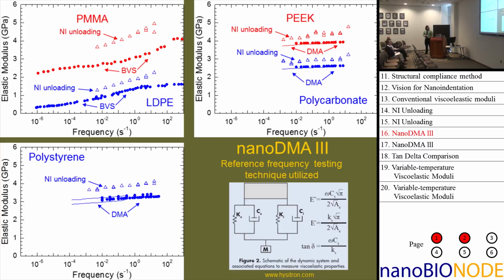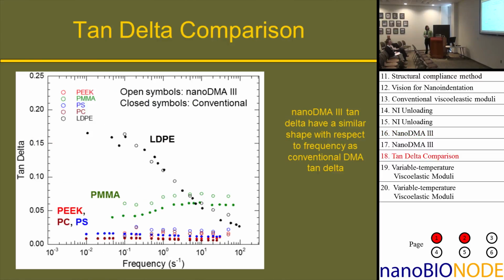So there's, of course, another way to try to measure the viscoelastic moduli, and that's to do these dynamic tests, where basically you load up the indenter and then apply a sinusoidal load to it and measure the load and displacement, and you can calculate a storage modulus that way as well. And we do that on these exact same experiments. Again, we see that it's always systematically higher, but we continue to capture the shapes of these curves. So another thing with the dynamic indentation is that you can also easily calculate a tan delta. And the tan delta is related to the shapes of these curves. And if you go through all these materials, you also see that the tan delta lines up pretty well. So this is kind of gaining confidence that we're potentially making physically meaningful results.